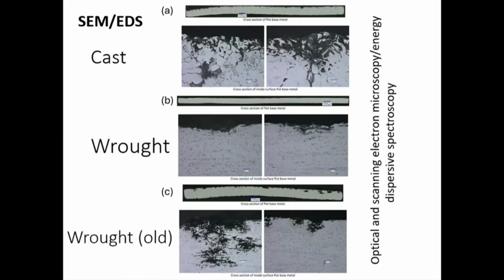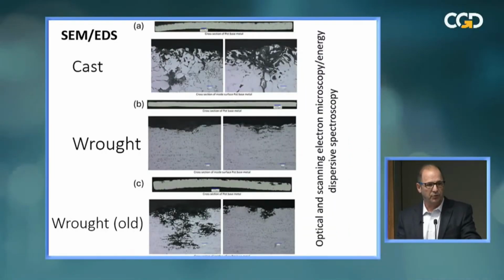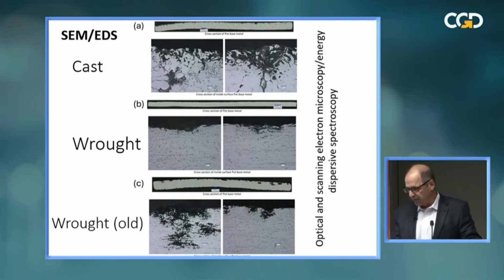Why? So we looked at some of these pots, the cross-section, using SEM and EDS, and we looked at cross-sections of the pots. And you can see the upper one is a cast pot, and the two lower ones are wrought pots, okay, from rolled aluminum. And first I'll show you the two bottom ones.